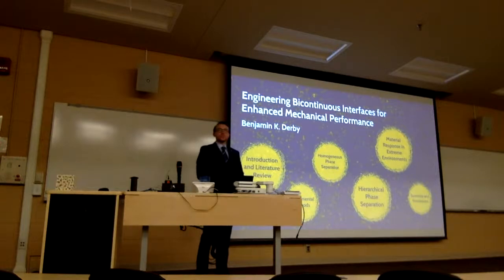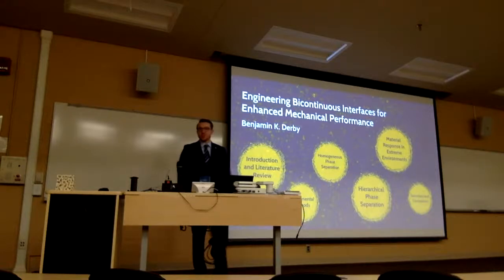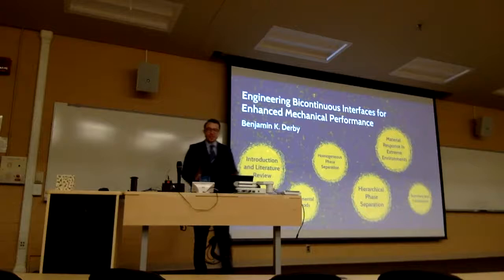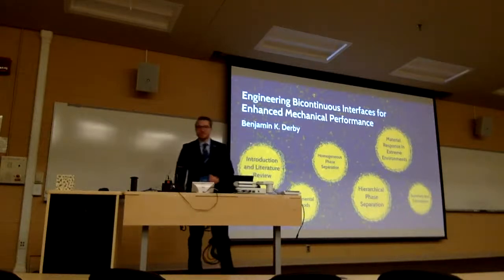Somebody else. I actually have the same question. If you're changing the substrate itself, are there any effects from starting roughness or surface energy? Yeah, that's a great question. We only used one substrate in this study, but we suspect that by changing the surface energy of the substrate, we could potentially change the initial structure of the phase separated morphology. We'd have to see what the difference in surface energy would be between the depositing film and the substrate.